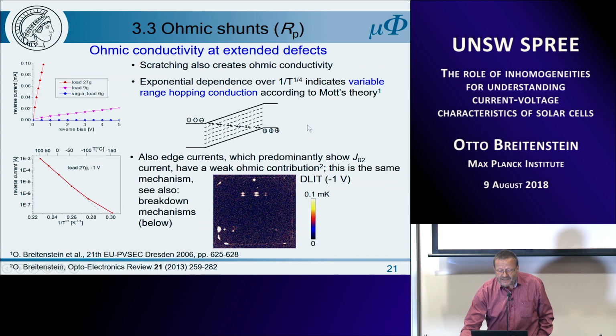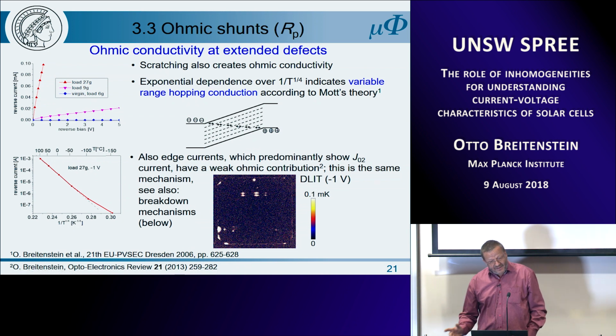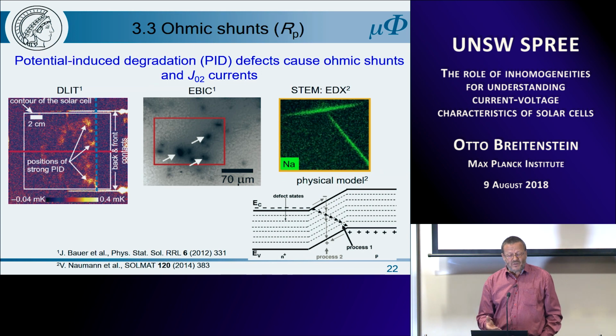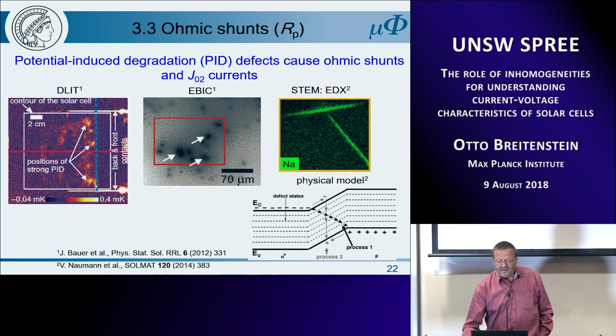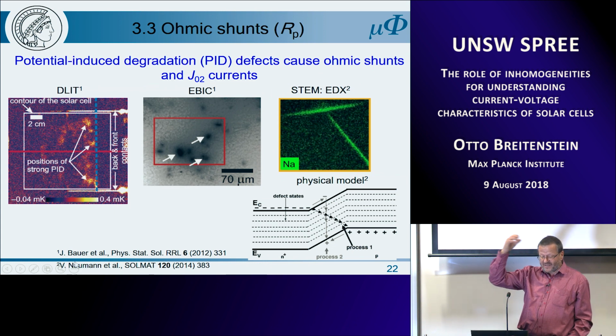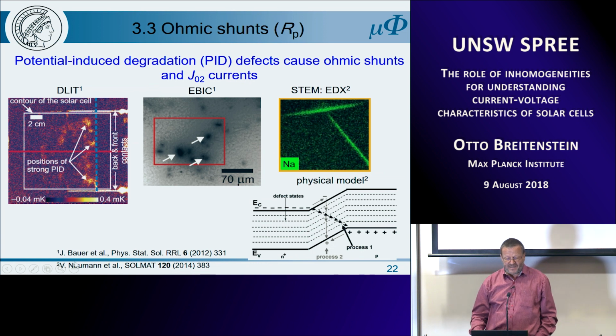And we see here that's a monocrystalline cell. Don't consider the signal in, there's a lock-in tomography at -1 volt, and we see we have a very weak but measurable ohmic current here in these edge regions, where we also have seen the J02 current. Okay, other sources of ohmic shunts are due to potential induced degradation. They cause ohmic shunts and J02 currents, and we also contributed to these identifications together with a group of Volker Naumann and co-workers at Fraunhofer CSP in Halle.